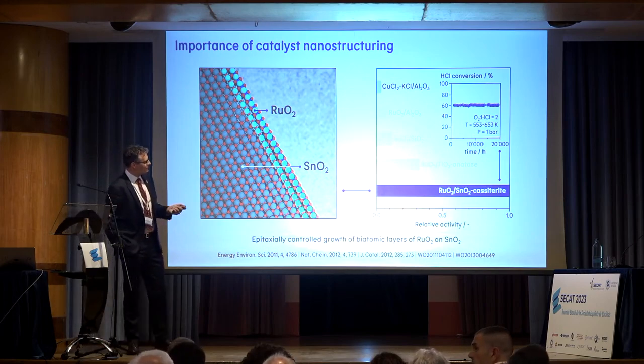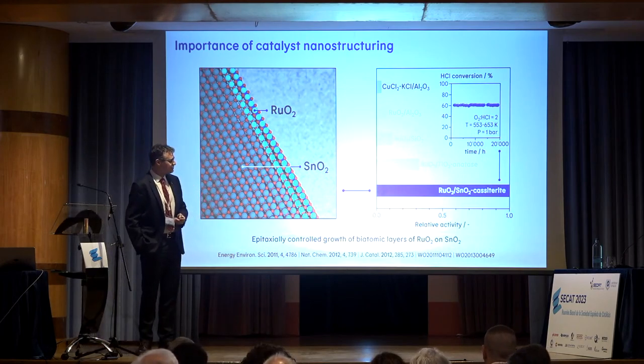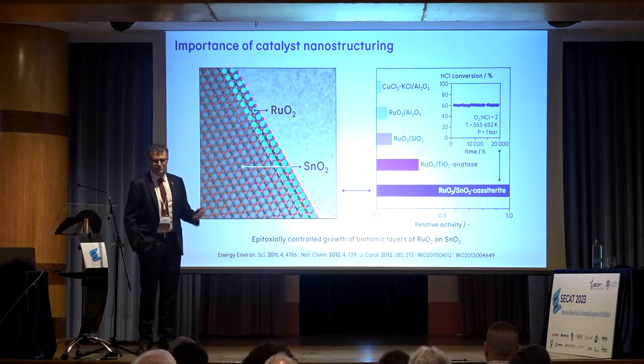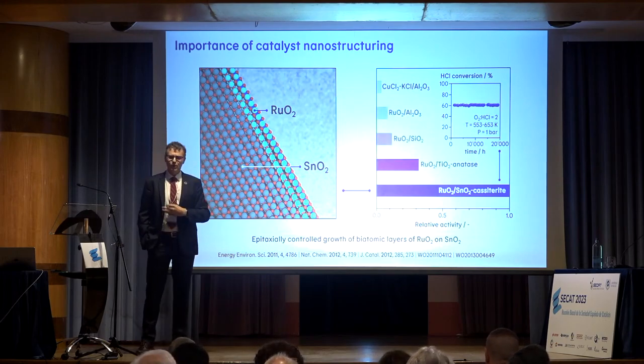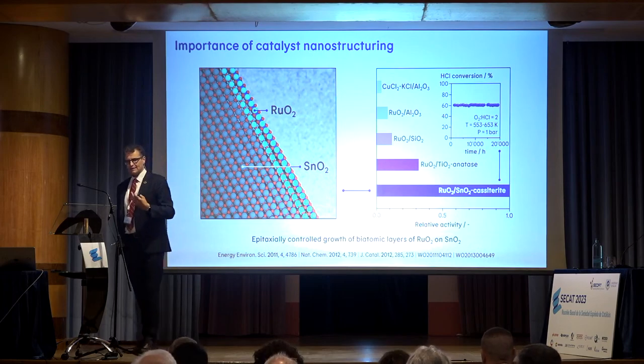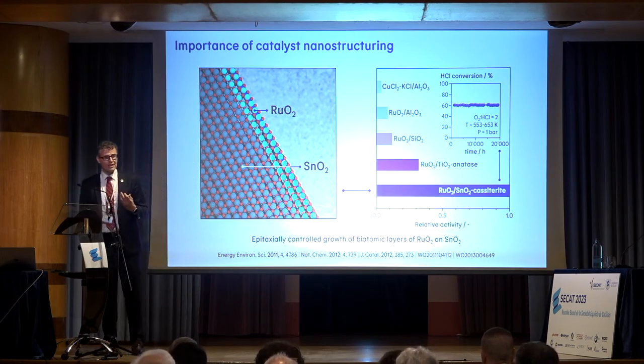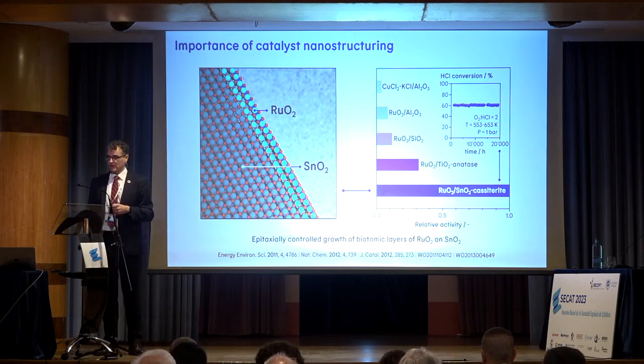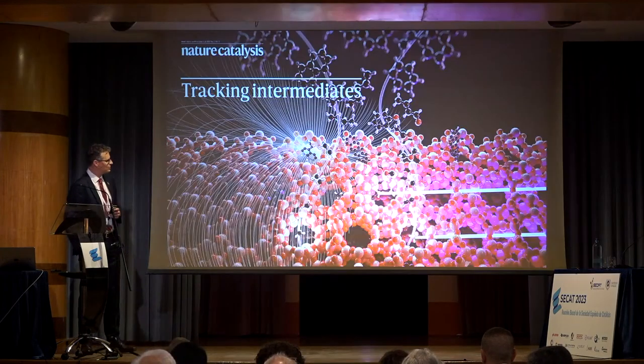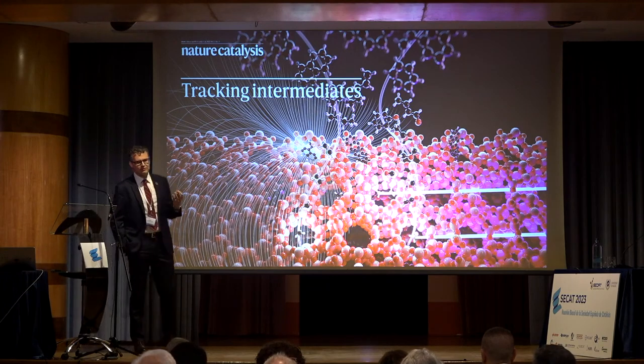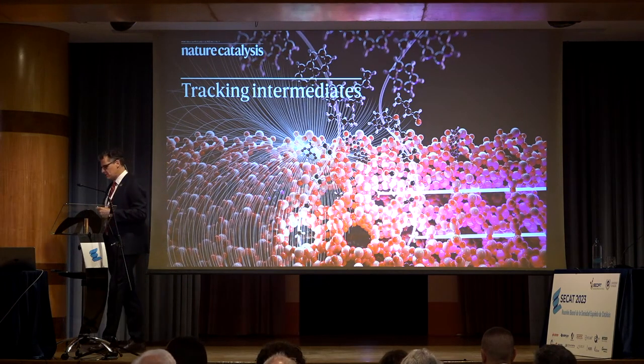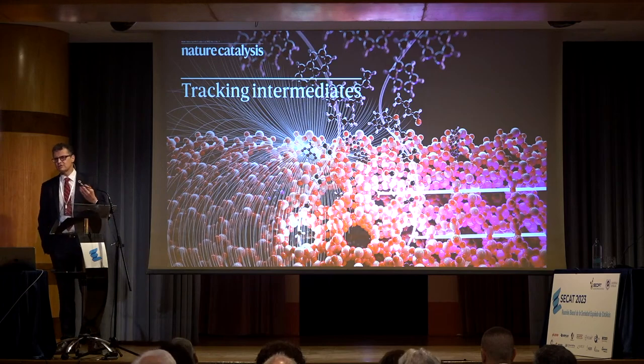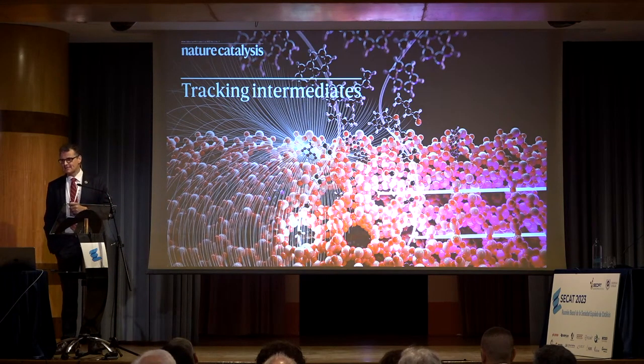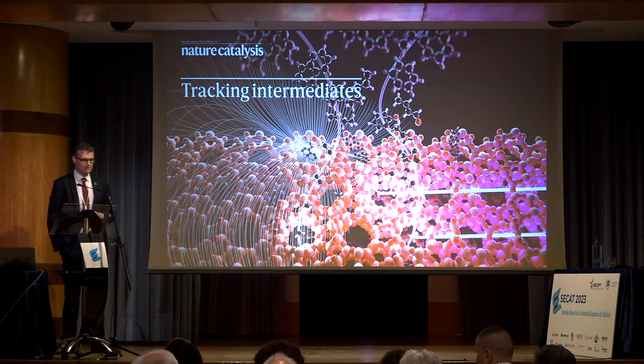The stability is great, as you can see there, 20,000 hours on the stream. And as I was mentioning before, if you put ruthenium oxide on other supports where you don't favor epitaxial growth, the catalytic activity is inferior. Most important, these materials are not stable. They're not stable under reaction conditions. There has been a lot of efforts in understanding this chemistry using a wide range of operando techniques to understand what halogen chemistry does and how to moderate or control the halogen chemistry on these catalytic surfaces.